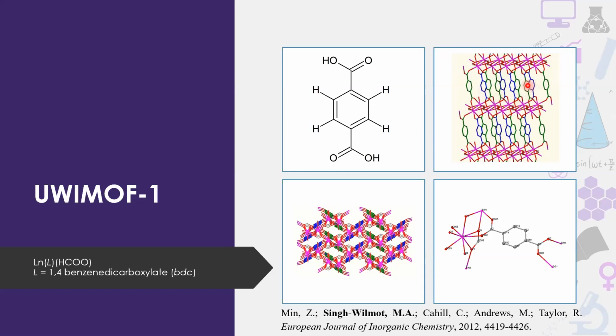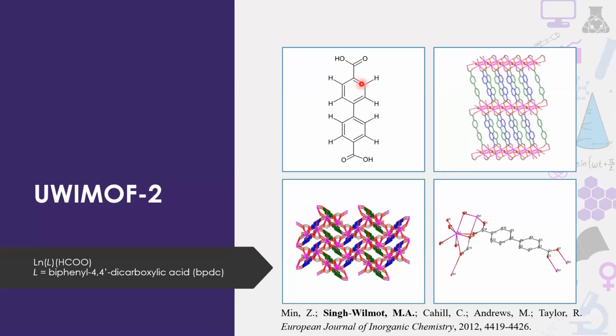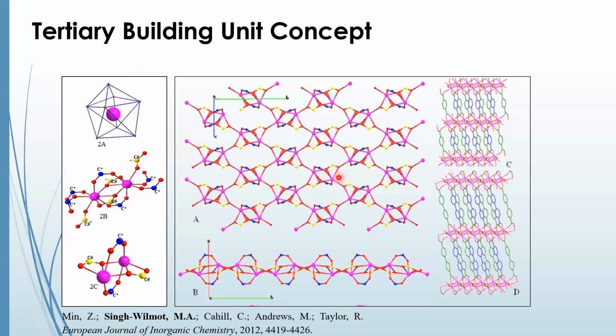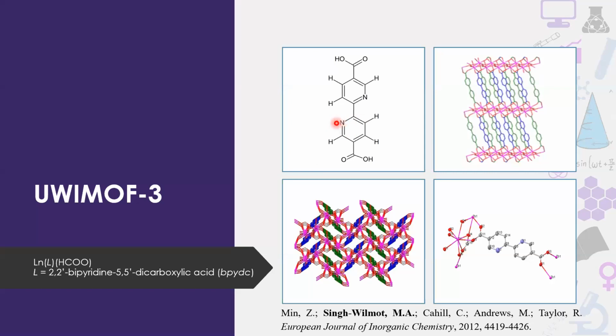We were able to reticulate, so we deliberately go in and change the nature of those linkers, and found that we could make UWI-MOF 2 if we change the linker, extending the linker chain using biphenyl dicarboxylic acid. The nature of the framework structures all feature this brick wall, this two-dimensional inorganic brick wall motif. And basically, this is entirely made out of building units, which we call the tertiary building units. So since all of these structures were showing this TBU feature, as we call it, we took advantage of that to make even more, and we were able to change the functionality in the linker.